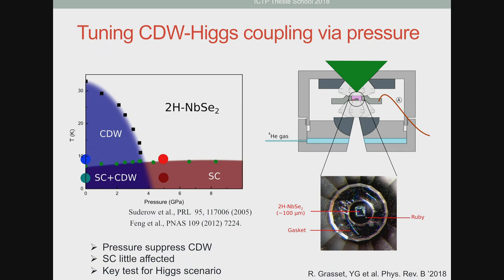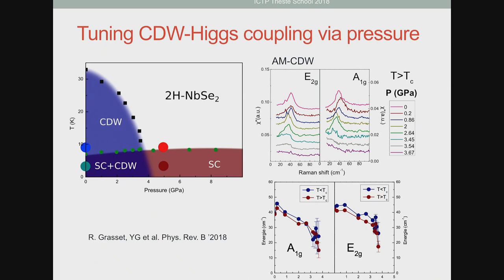So this is a key test for this scenario, to see if the CDW state is really crucial for the observation of this peak. This is Raman measurement as a function of pressure, first showing the data above TC, so essentially a horizontal line above TC. This is tracking the pressure evolution of the amplitude mode of the charge density wave phase. Here I'm showing you experiments in two different polarization configurations. In both, you can see that the peak of the amplitude mode of the CDW state vanishes, and by the time you reach 4 GPa, it's essentially absent. So you have really killed your charge density wave state.